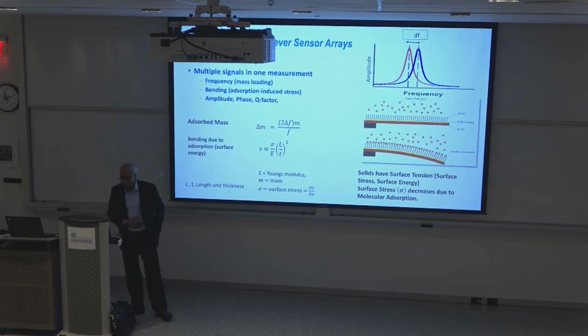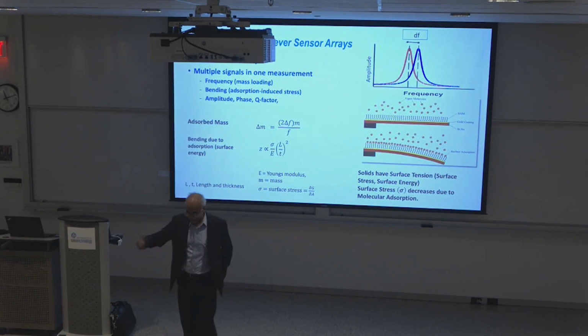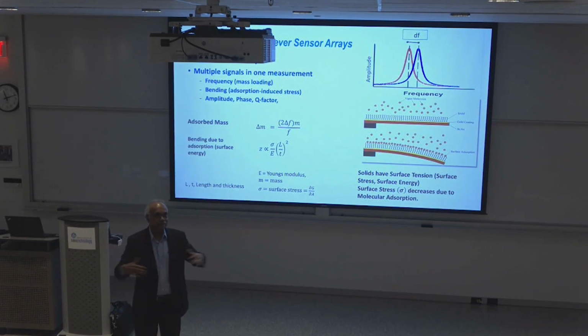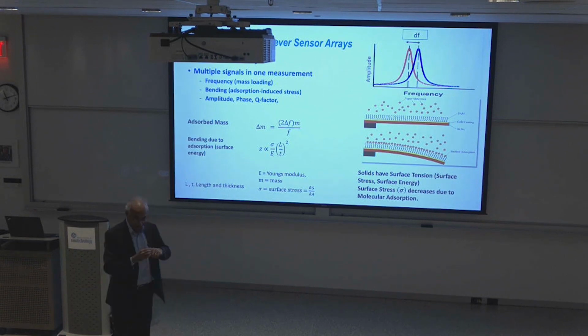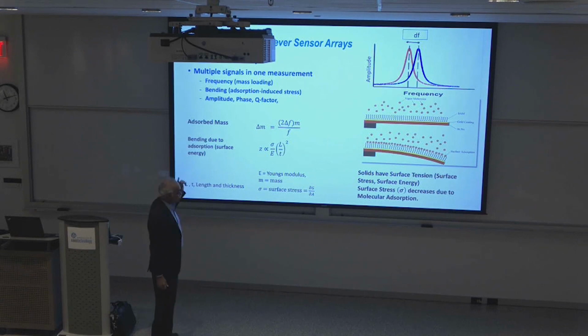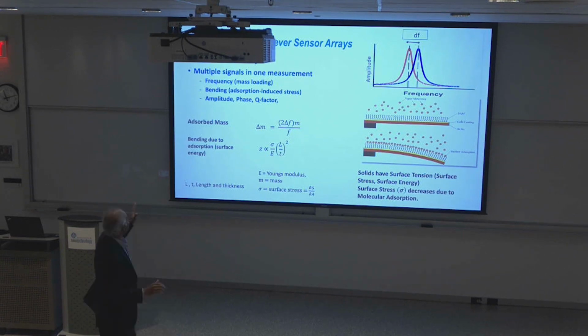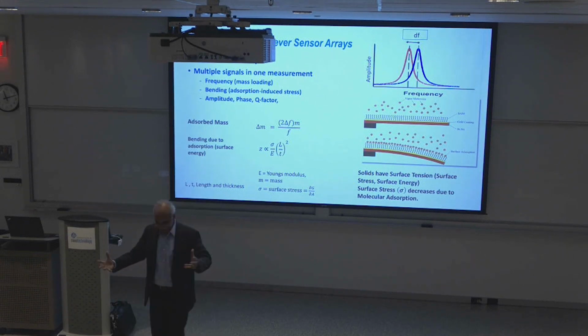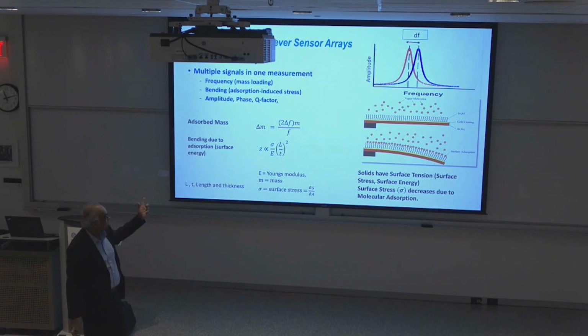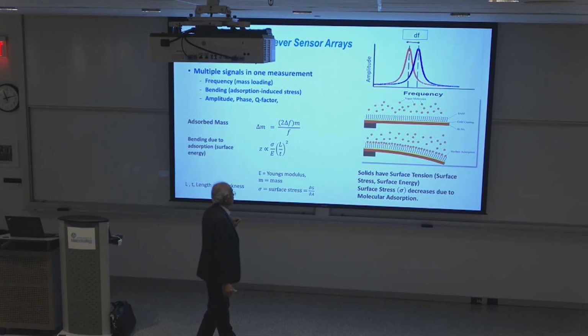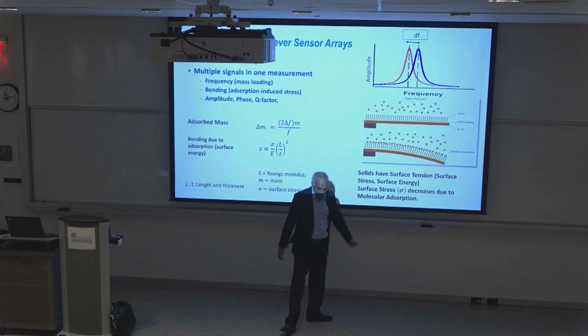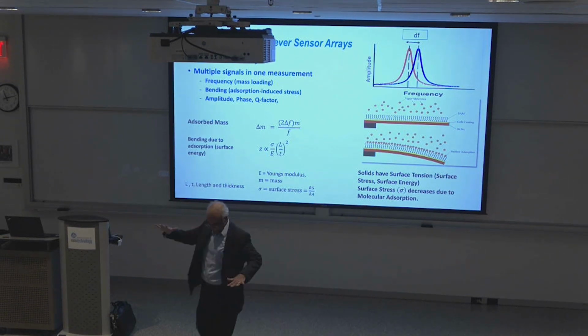The cantilevers are easy to make, and with a clean room you can make them easily. You can make them with piezoresistive readout, so it's a hard electronic readout. You can make them smaller and smaller, from a few microns in size all the way to 500 microns. The beauty of the cantilever is that it gives you multiple signals at the same time. It will give you the frequency change coming from mass loading, assuming molecules are absorbing on the surface and the mass changes, and it can detect that. If we confine our molecular absorption to only one surface, then the surface stress changes. So differential surface stress makes the cantilever bend.